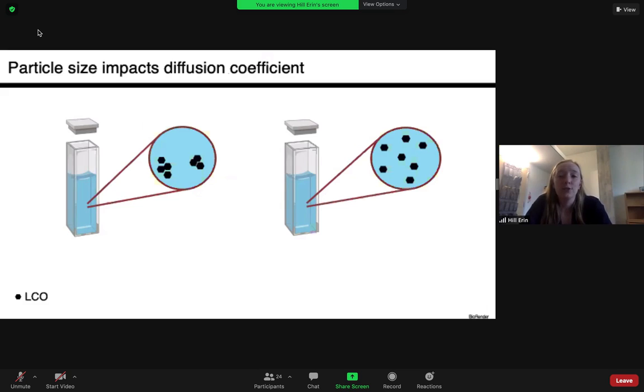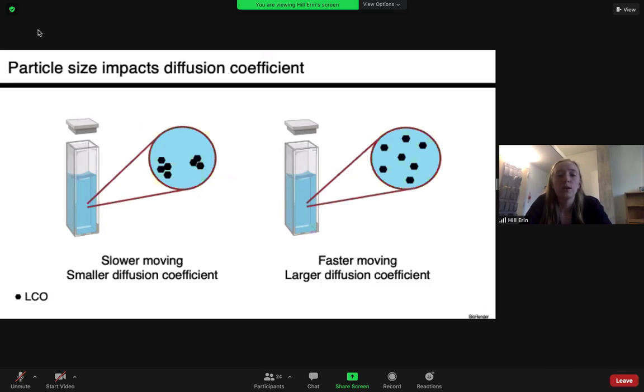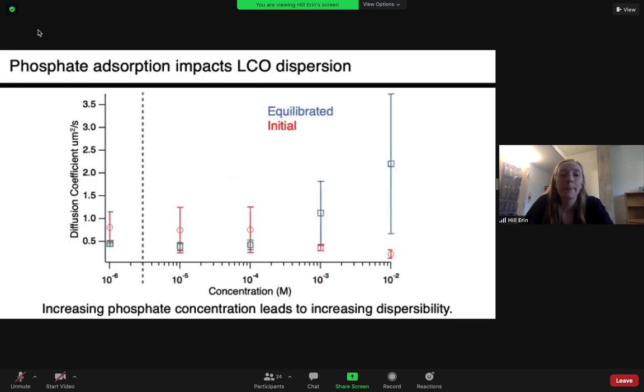One thing that impacts diffusion is size. And so generally, larger particles move more slowly than smaller ones, and so we'd expect the LCO nanoparticles that have aggregated together to have a smaller diffusion coefficient, while more dispersed nanoparticles would have a larger diffusion coefficient. Based on the zeta potential data, we were expecting that the LCO phosphate particles would have a larger diffusion coefficient, indicating that they were more dispersed. And this is what we see.